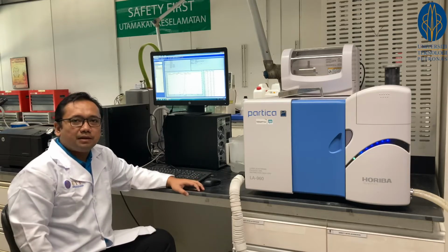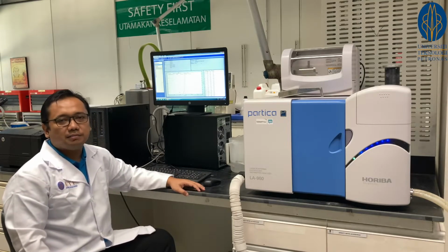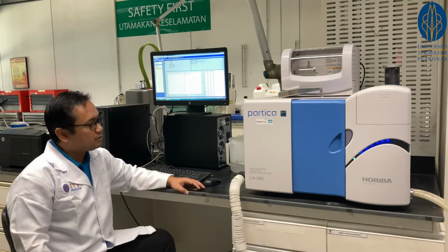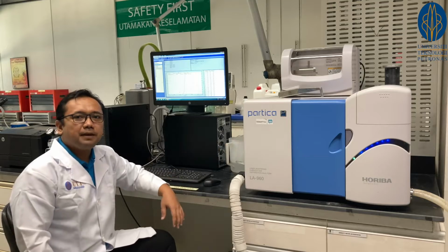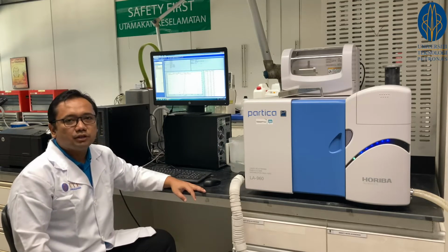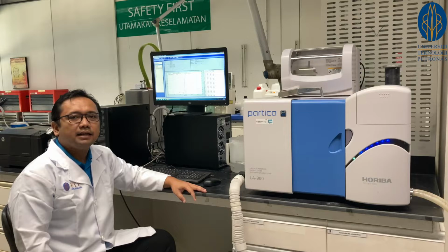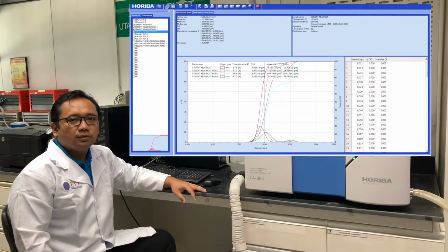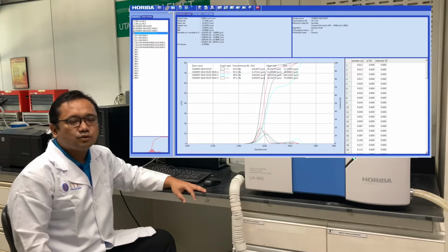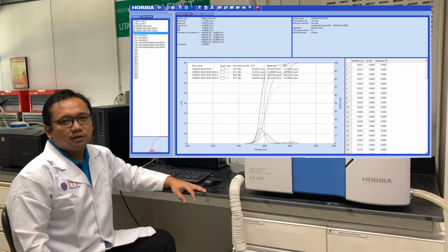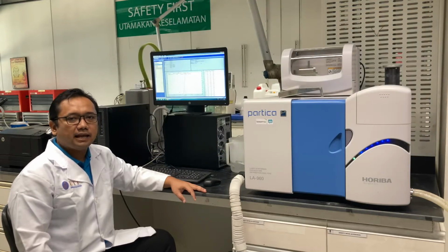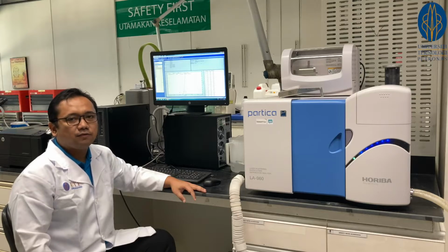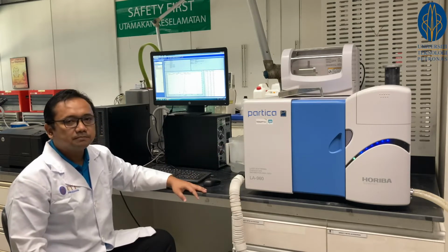Since the dry sieve capability is limited to the minimum of 63 micron, we extend the in-depth analysis of sand PSD using LPSA. The LPSA can measure the size distribution of sand ranging from 10 nanometer to 350 micron. Thus, we are able to analyze the sand size of lower than 63 micron. A comprehensive method towards PSD analysis and synthetic sand development could be done using both dry sieve and LPSA methods.